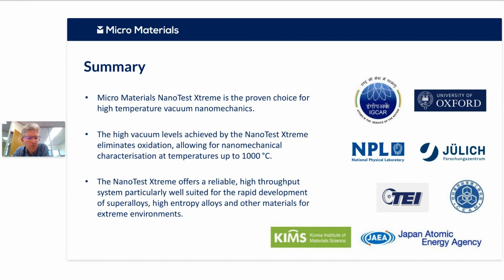control by active tip heating of the indenter and the sample. It really gives these ultra low thermal drifts that give you reliable results at very high temperatures, particularly where you get a lot of indentation creep happening in many materials. So you really do need to get a good handle on the thermal drift and minimize it so your results are reliable. Applications include superalloys, high entropy alloys, ceramics, and other advanced materials, hard coatings as well. And there are just a few of our users there on the right for the Xtreme system. Thanks very much. That's it.